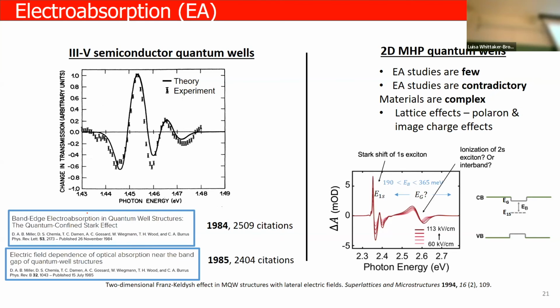And where are those lattice effects coming from? So from here, we all agree that this peak is related to excitons. But now the difference that you have from this peak to whatever is happening over here will determine what your binding energy is. So if you don't know where to set that, then you will just have that variation in your exciton binding energy, okay? So now the problem is, what is this peak, okay? And what is this one too, right? All right, so that is what we actually wanted to understand.